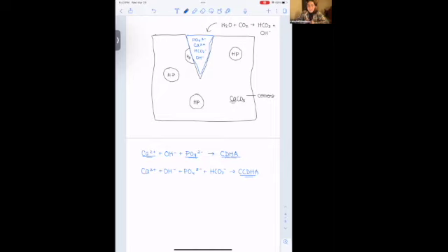But I also wanted to use this as kind of a lesson in reading papers carefully. So they were able to get 95% healing, which is more than traditional concrete does. However, the compressive strength, so that's what they were measuring healing by, is the change in compressive strength. The compressive strength of the cement that's impregnated with this hydrogel was actually just significantly lower than traditional concrete. So while they were getting 95% healing, the healed concrete was still not as strong as the concrete would have been to start with if they hadn't put the hydrogel with phosphate in there. So I do think this has a lot of potential. I just don't think that this paper necessarily was being as honest as they could have been.